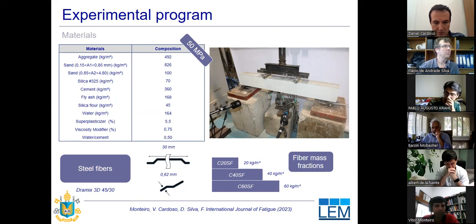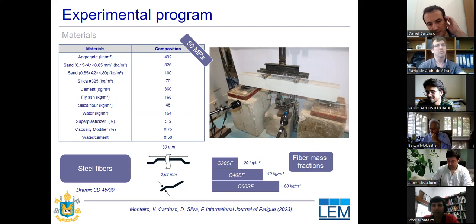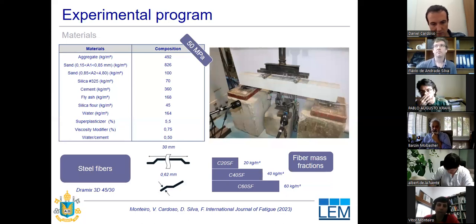The composition presents two types of sand, the use of silica, fly ash, superplasticizers, and viscosity modifiers in order to reach the flowability needs for the composition. It also used a water cement factor of 0.50. The used steel fibers were hooked end steel fibers with an aspect ratio of 45 and 30 millimeters of length. Three fiber mass fractions were added to the mix: 20, 40, and 60 kilos per cubic meter.